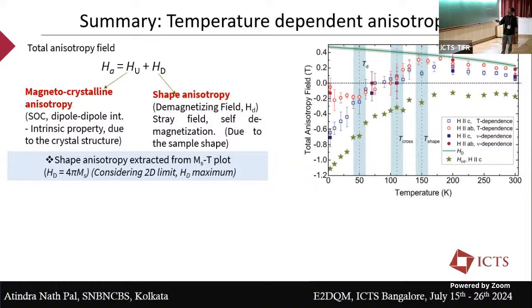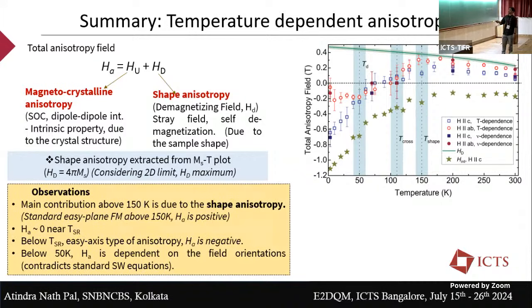Now why do you have a change in anisotropy? Of course if you subtract this shape anisotropy value from this total value, you can see that this magnetocrystalline anisotropy is overall negative, but it has a dramatic change near the spin reorientation transition. Okay, it actually increases very much after the spin reorientation transition. And more importantly, near this 50 Kelvin,